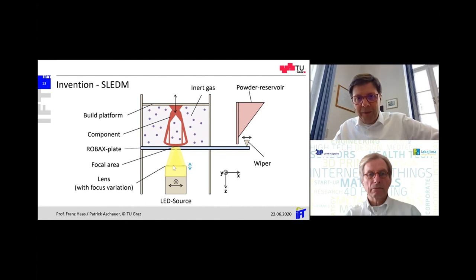You have a light source which can be focused via a lens configuration, one lens or more lenses. And so we can vary the melt pool, the melt area, and therefore we can focus more or less. And the amount of powder is a very small amount of powder. You have here a powder reservoir, and we spread the powder on the heat-resistant glass plate only for less than 1 millimeter. And the focus area is above the glass plate and between the already built part